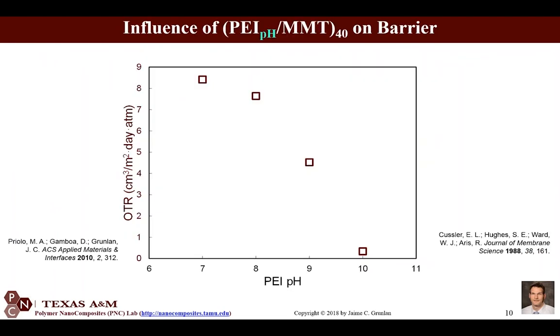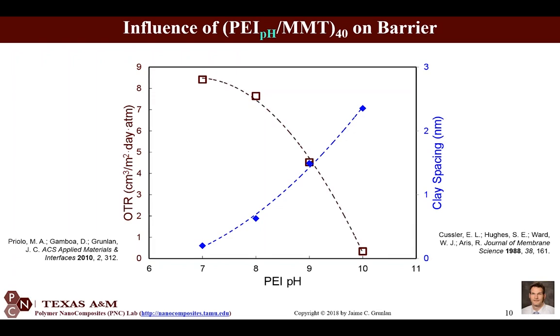A perfect example is polyethylene imine, which I'm showing as PEI here, with pH as a subscript in green. And then MMT is montmorillonite clay platelets, something like 200 nanometers in diameter and 1 nanometer thick. When I layer that cationic polyethylene imine with montmorillonite clay, here it's all 40 bilayer films. That means 40 clay and polymer layers. What happens is my oxygen transmission rate is decreasing as my clay spacing is increasing,